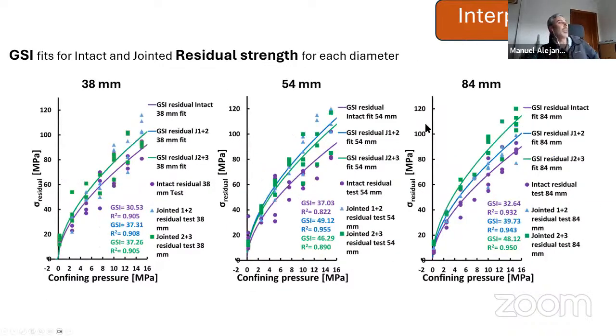And for the residual strength, we see that the lowest values are those obtained for the intact samples, for all the diameters. And we think that they are due to the energy released during the break, because the intact samples tend to accumulate more energy, so they produce more damage. So we expect GSI values lower than the ones obtained for the jointed specimens.